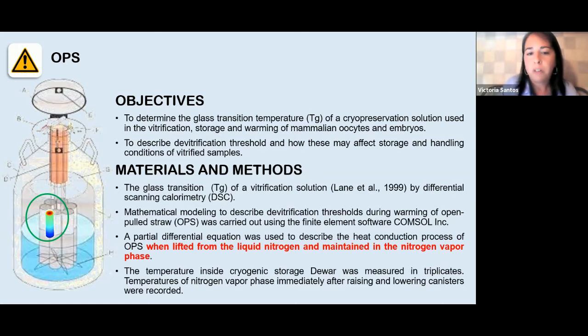So we solved the partial differential equation to describe the heat conduction process of OPS when we lifted the OPS from the liquid nitrogen and maintained it in the nitrogen vapor phase. We also measured the temperature inside a cryogenic storage dewar when we disturbed the nitrogen vapor by raising and lowering the canister.